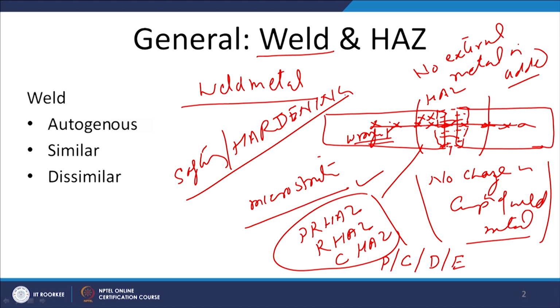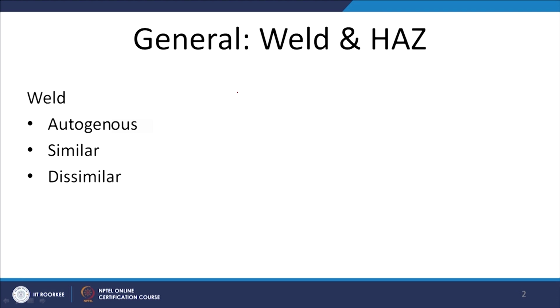depending upon the kind of the metallurgical transformations which are taking place in the weld zone. For example, most metals like precipitation hardenable systems, work hardenable systems, and dispersion hardened systems, when they are welded by the fusion welding process, mostly we see, even for autogenous welding, where no change in chemical composition of the weld metal is taking place, just the faying surfaces are fused, the weld metal is found to be of poorer mechanical properties due to the unfavorable metallurgical transformations as compared to the base metal.